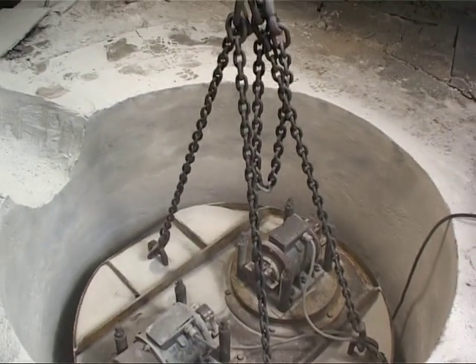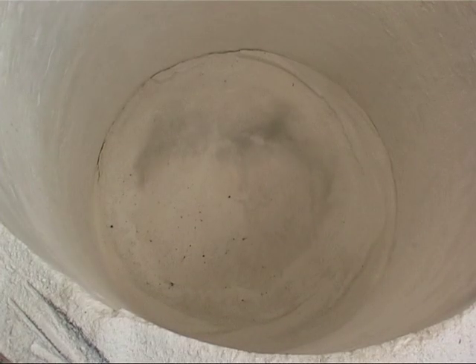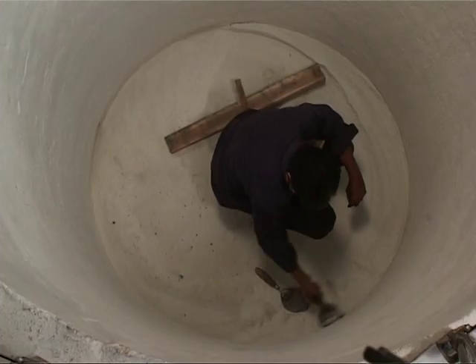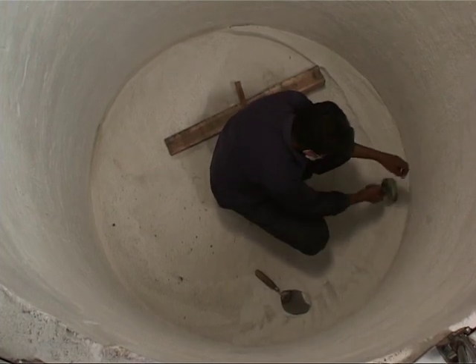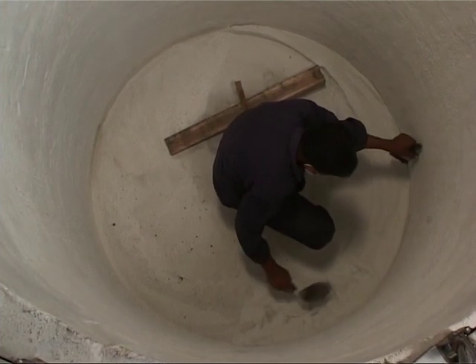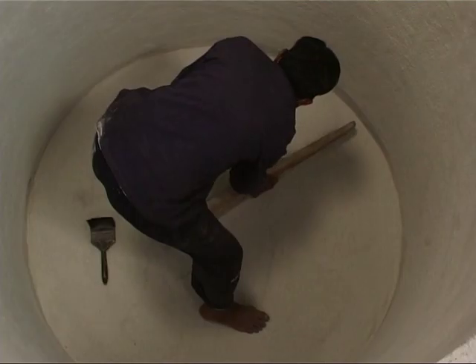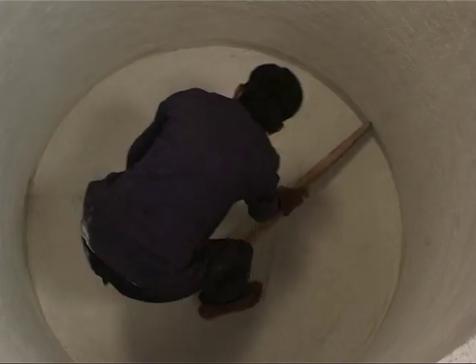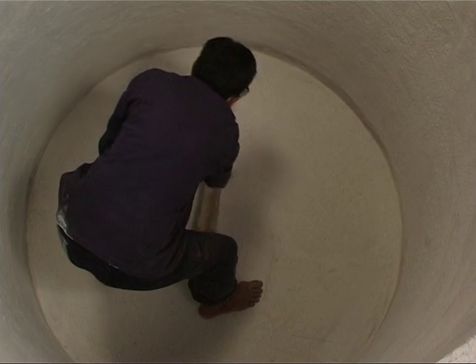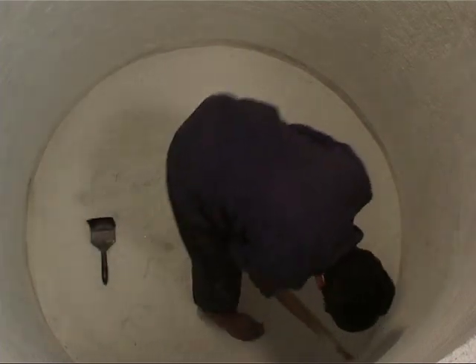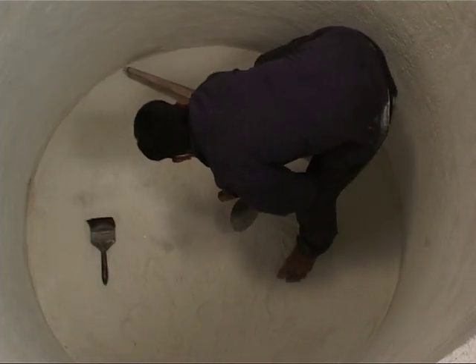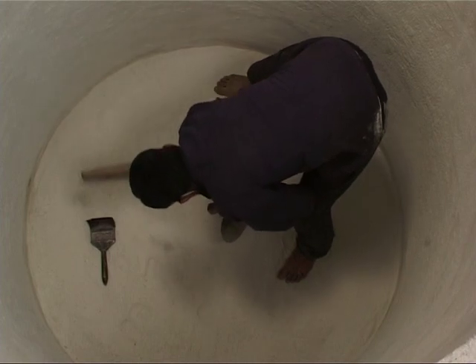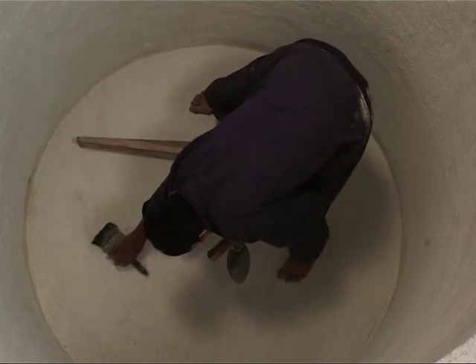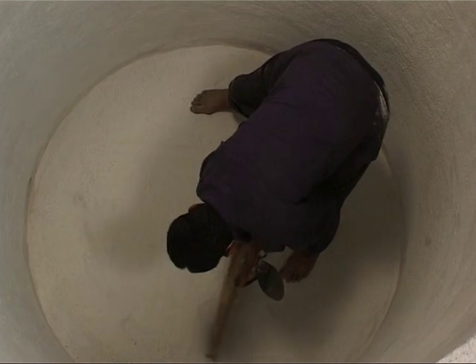Remove the bottom plate and scrape off 10 to 20 mm of loose mix to a smooth horizontal surface. Check with the spirit level. After weighing the scraped off material, keep a record of net weight of ramming mix packed into a given height in order to calculate packed bulk density. Higher the density, better is the lining life.